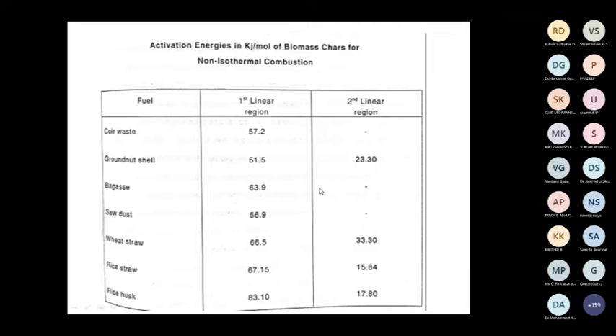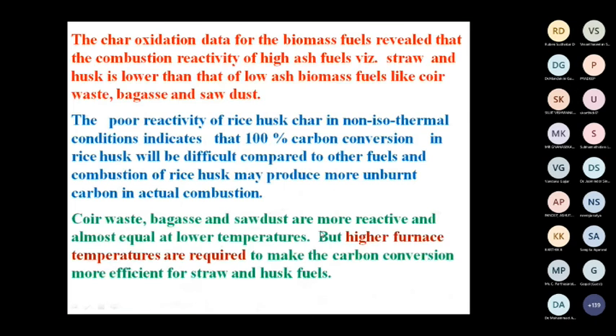So this is the activation energy for all the 7 biomass fuels. Char oxidation data for the biomass fuels revealed that the combustion reactivity of high ash fuels like straw and husk is lower than that of the low ash biomass like coir waste, bagasse and sawdust. The poor reactivity of rice husk char in non-isothermal conditions indicates that 100% carbon conversion in rice will be difficult compared to other fuels, and combustion of rice husk may produce more unburned carbon in actual combustion. Coir waste, bagasse and sawdust are more reactive and almost equal at lower temperature. So higher furnace temperatures are required to make the carbon conversion more efficient for straw and husk.